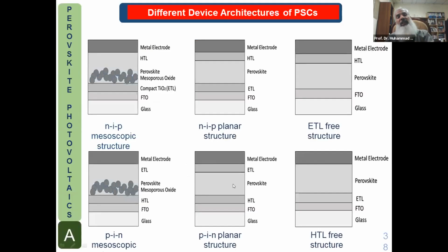So these are the different architectures, designs of perovskite solar cells. One is this one where people start with the glass electrode with fluorine tin oxide coated on that. Then a thin film of compact titanium oxide is used as electron transport layer. Then there is a mesoporous layer of titanium oxide, and then there is a perovskite layer, then a hole transport layer, and finally gold or silver are used as metallic electrodes, but that's expensive.